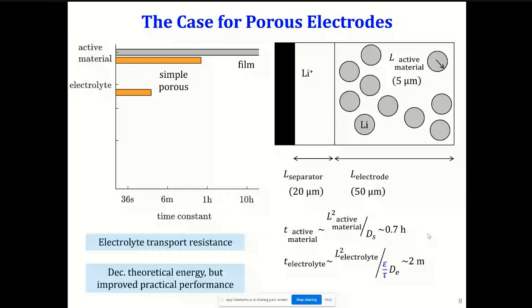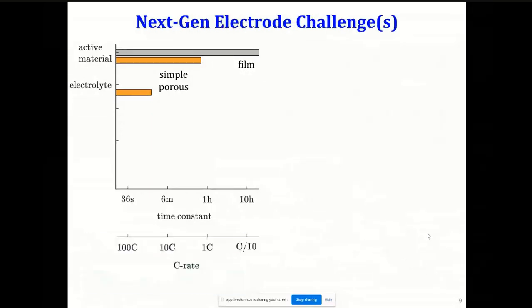Now, this particular way of thinking in terms of time constant helps us easily identify what are the next generation challenges for porous electrodes, right? And what I've done is I've added another axis at the bottom, which is essentially the reciprocal of this time constant. So if someone who is more familiar with the battery says that I'm doing a C/10 charge, it means that it's roughly going to take them 10 hours to charge these cells, right? Equivalently, if someone says I'm doing a 10C charge, that means that it's going to take them 6 minutes to charge it. Equivalently, if you do a 10C discharge, it's going to empty your cell in 6 minutes.